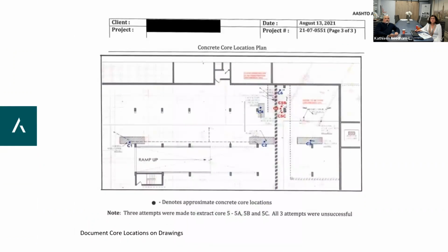In this case, the contractor mapped out where he took the cores, and he notes that 3 attempts were made at cores 5A, B, and C. All 3 attempts were unsuccessful because he reached rebar and was not able to drill all the way through. There was no infrared done on this structure, so they cored blindly.